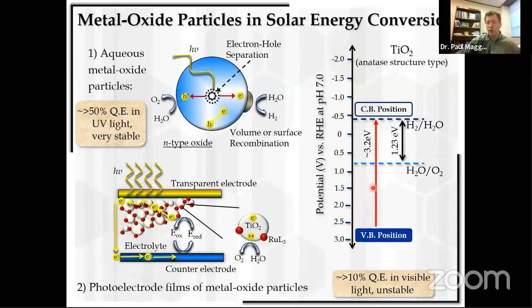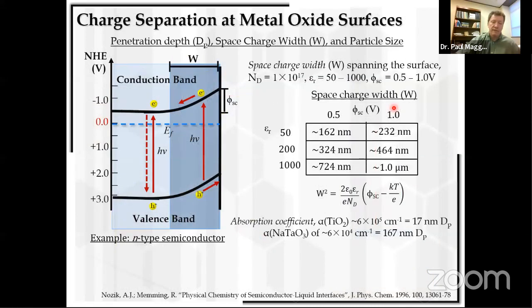right? Such that you can appropriately position the valence band position right below this redox couple while also maintaining the conduction band position here, right above this redox couple, and then drive them very efficiently using sunlight as the electron is promoted from the valence band to the conduction band. And so to understand this, we have to take a look at what the band energies look like at the electrolyte solid interface.